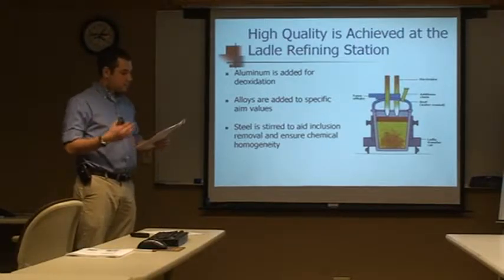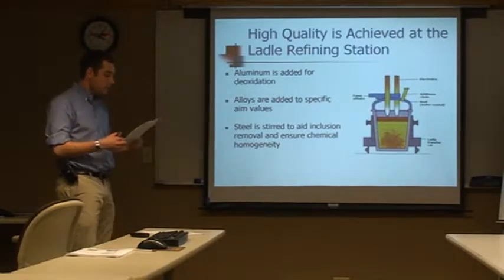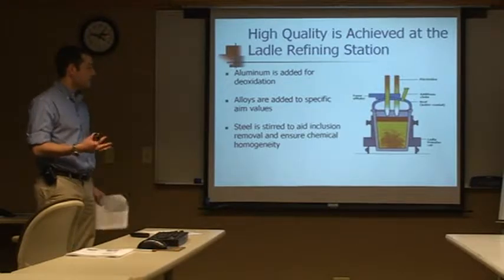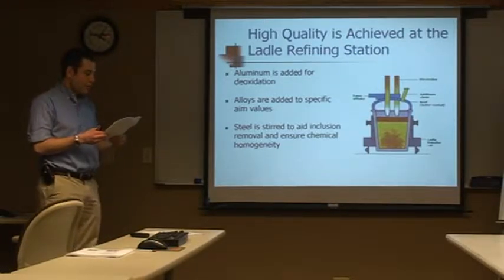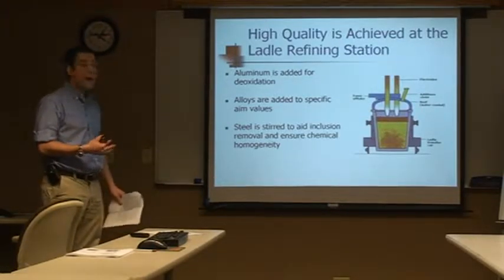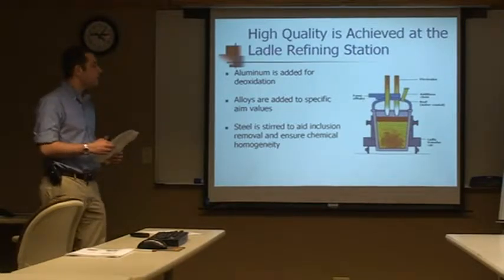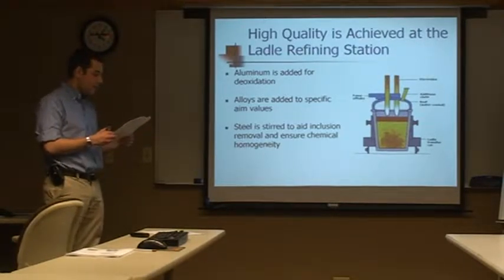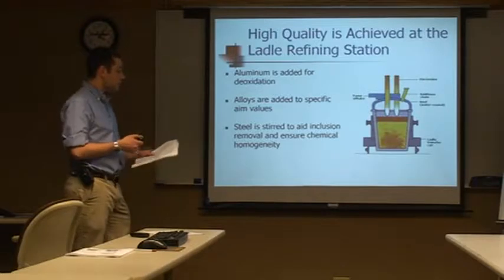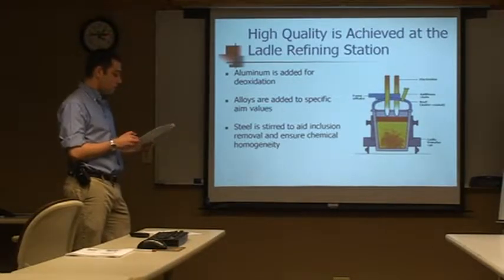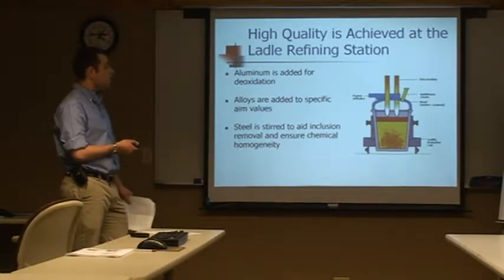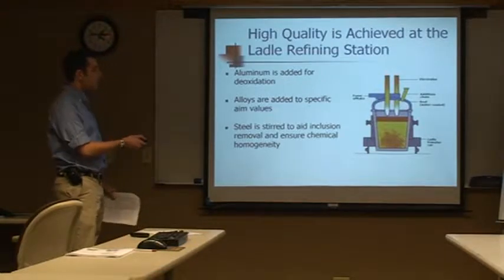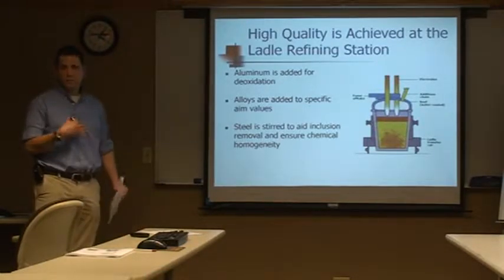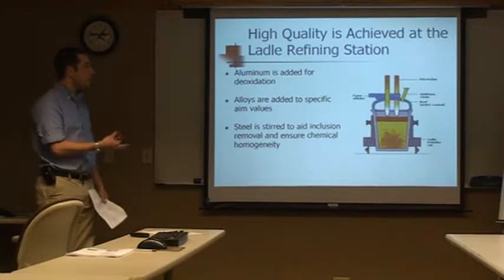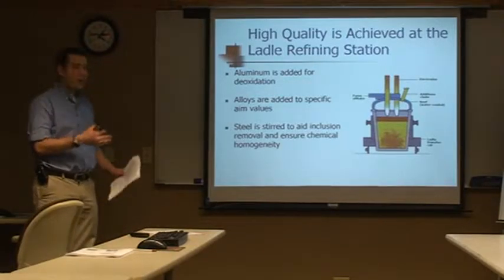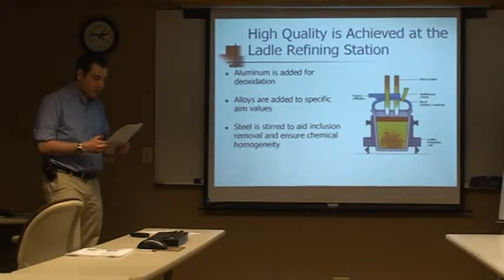After tapping, the ladle's moved over to a ladle refining station, which is where we do most of our alloying and get the steel up to any kind of grade that we're trying to make. The ladle station is equipped with electrodes just like the arc furnace, as you can see here. But these aren't really for melting anything because we already have a liquid steel bath. These are just to maintain the temperature.